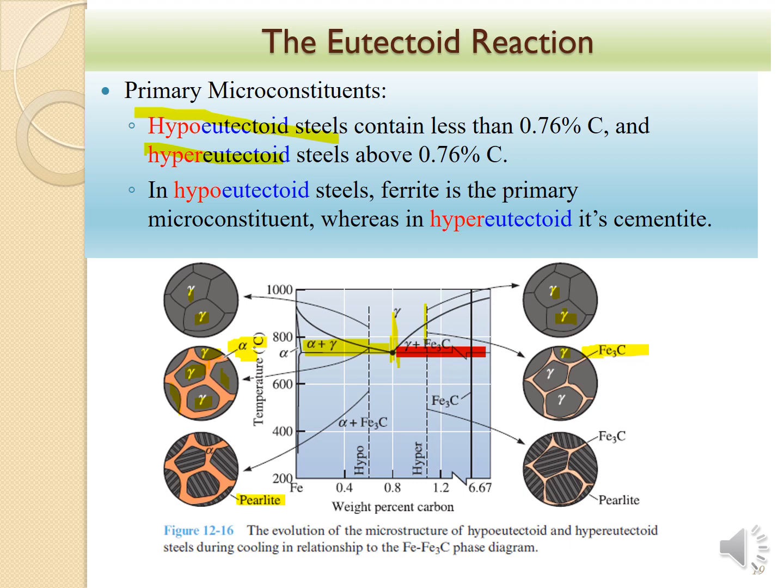That smaller orange region is the cementite. At the eutectoid temperature, the eutectoid reaction takes place, and all the austenite will transform into pearlite. So that means for hypereutectoid, it is cementite plus pearlite.